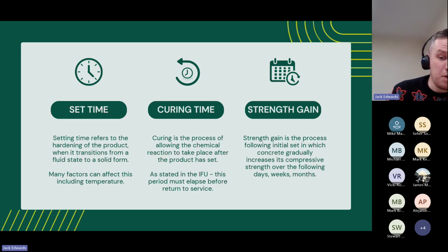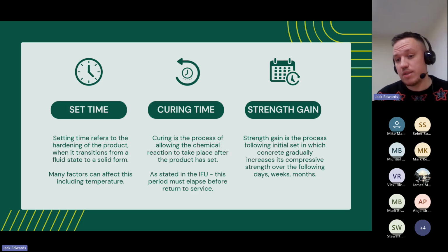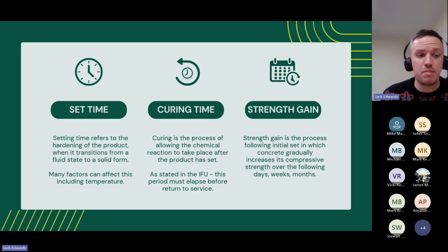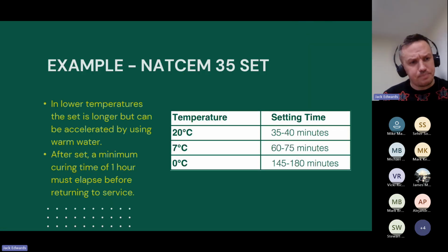The curing period with Natcem products will always remain the same. So in a lower temperature, although the set will be longer, the cure will still be 1 hour after the initial setting time. In higher temperatures, although the set will be quicker, the cure will be 1 hour after the initial setting time. So that period always remains the same.